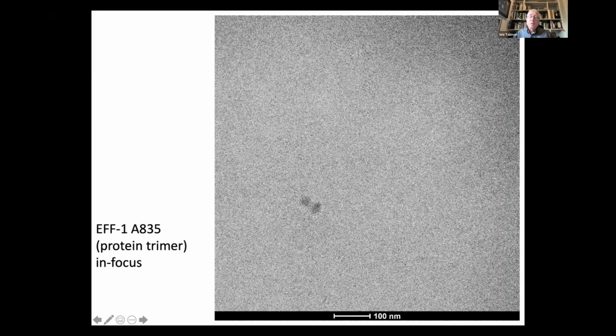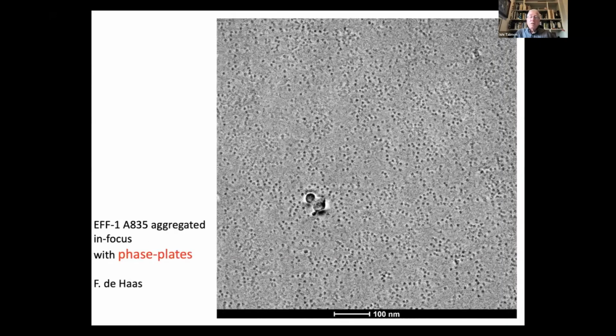When you turn on the voltage on the phase plate, then you see this. So going from this to that. Again, this is just as a reference, you can see here the little ice speck. So basically, we make things that are invisible visible. And in specimens such as EVs, this is really extremely important. All the data that we have taken and which Kelly has shown has been taken with these phase plates, which are a very nice device, which you can have on modern transmission electron microscopes.